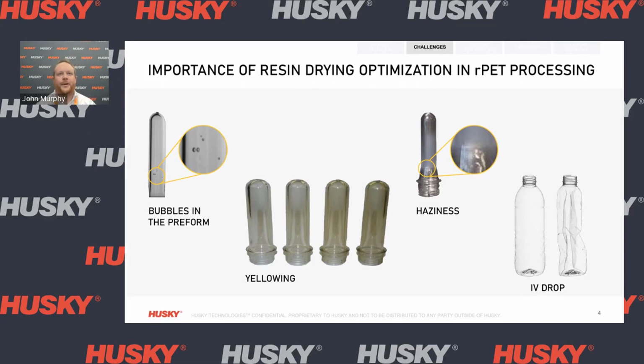Now, before we go deep into resin drying technology, I would like to start with why drying is important in the injection molding process. Some common issues that you can see are bubbles that are caused in the preform. This occurs when there's too much water still trapped in the resin, which boils off during the melt process. This can lead to visual defects as well as poor blowing behavior. We can also see yellowing of the preforms, which is caused by degraded resin, which occurs by excessive drying temperature or for drying the resin too long.